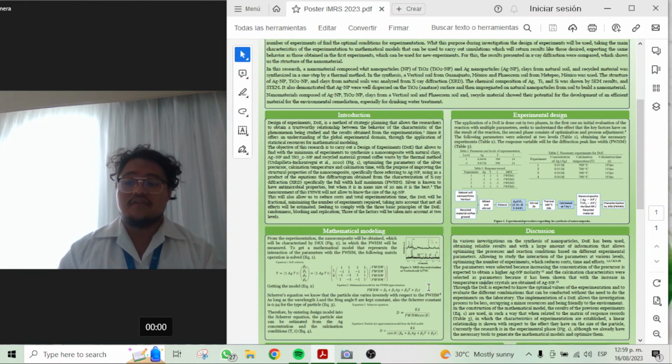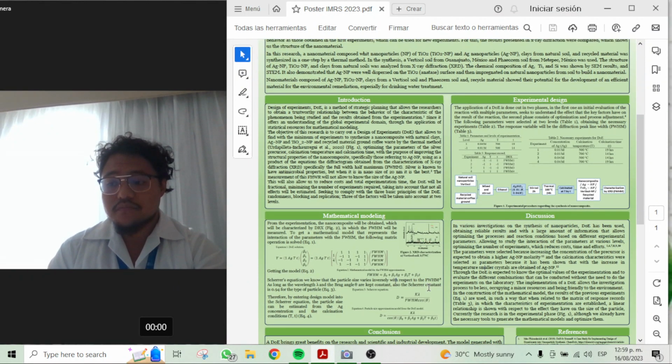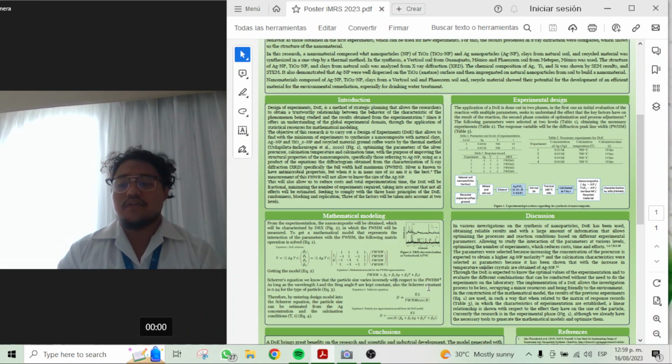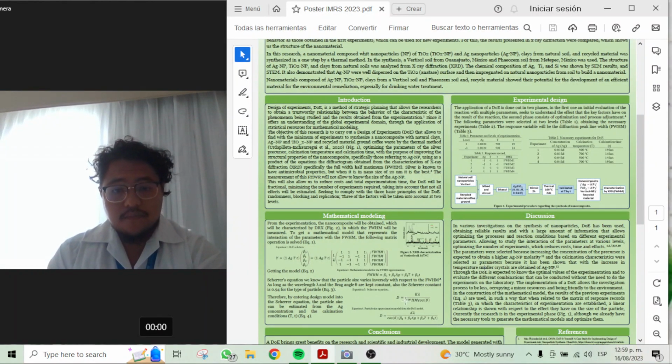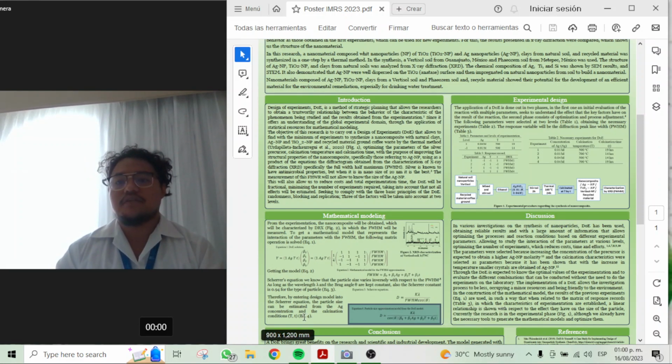This model has principal effects to the K parameters obtained in the experiment. We can use this model in the Scherrer equation to obtain the particle size in a simulation process and obtain the optimal conditions of experimentation to have silver nanoparticles with a 20 nanometer size.